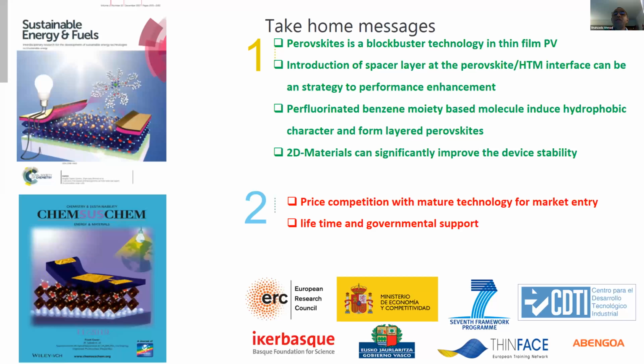especially fluorinated molecules, are ultra hydrophobic because the surface tension is very low in fluorinated molecules. They are ultra hydrophobic, and a perfluorinated benzene moiety can induce more stability here. 2D material also increases the stability, but it is inactive in terms of molecular exchange; in terms of stability and band gap alignment it is very good here. These are the very good things about perovskites.